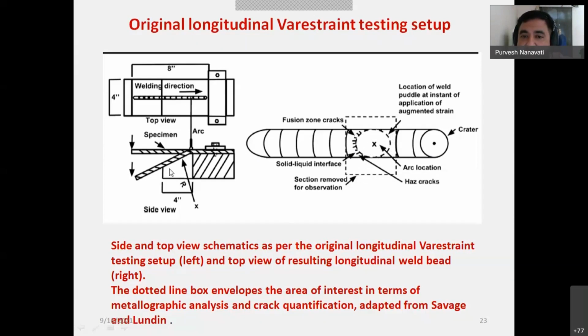So this is a side, and this is a top view of the original longitudinal Varestraint test setup. Now, this area you can see is where the weld ends. You can see the crater where the arc ends, so there will be some depression. And this is the location of the arc, and these are the heat affected zone cracks. It is labeled. And this section is removed for visual and microscopic observation.